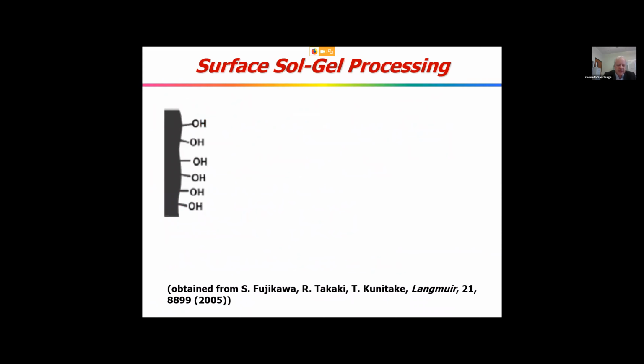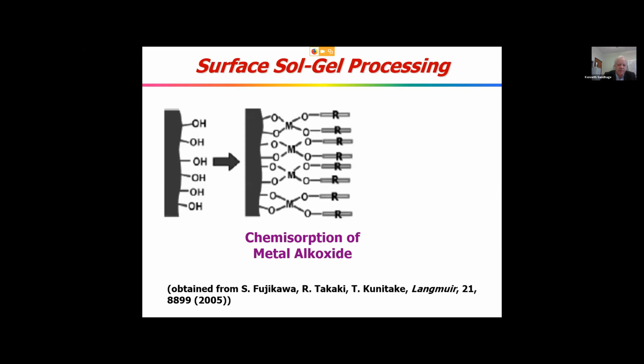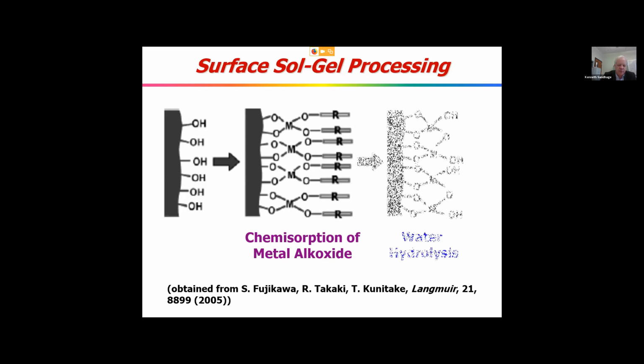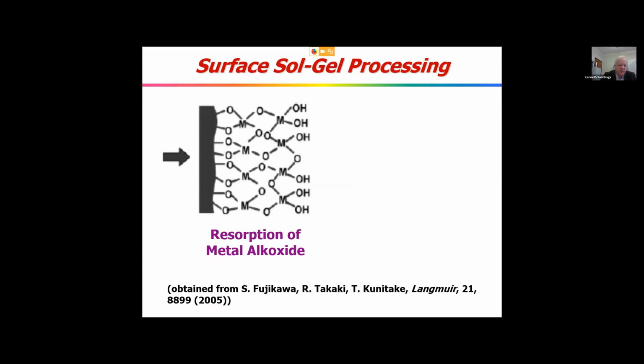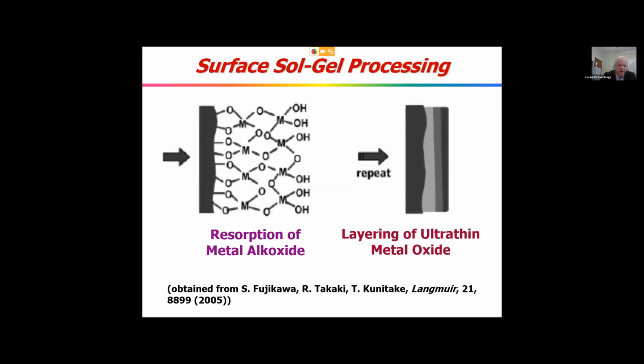So we utilize a technique invented by Kunitake's group in Japan called surface sol-gel processing. The idea is you take a hydroxylated surface like a pollen particle, expose it to a metal alkoxide like iron isopropoxide, for example. One or two of the alkoxide groups will react with one or two hydroxyls, liberate alcohols and form a metal-oxygen bond, and that will continue until you form a monolayer. The unreacted alkoxides that are dangling on the outside can be re-exposed to water to form hydroxyls, and this process can be repeated. Alkoxide, water, and layer by layer build up the desired material, and then burn away the underlying material to make a replica.